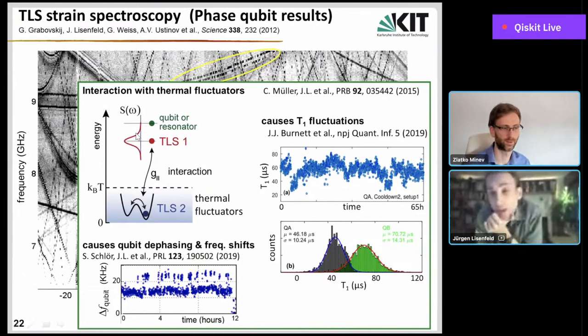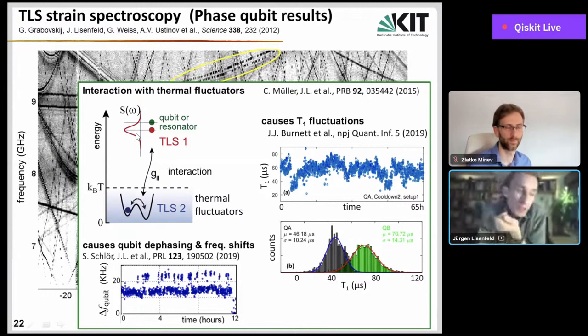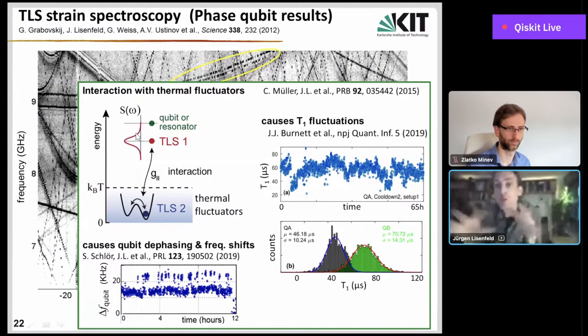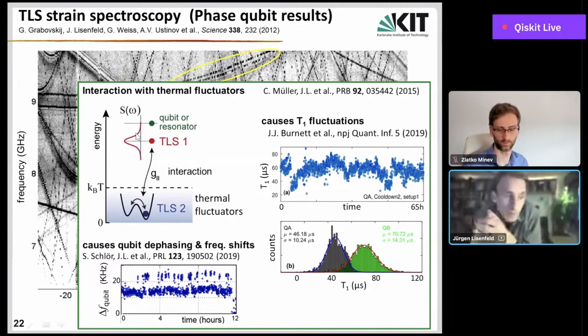There's, of course, also quasi-particles, which are known to cause fluctuations. These can exist, for example, if a cosmic ray hits the chip and generates an avalanche of quasi-particles, which would spoil the T1 time of many qubits. However, this is typically a short time effect. These quasi-particles recondense into Cooper pairs after a few milliseconds at the longest, and they would not explain these very slow dynamics here.